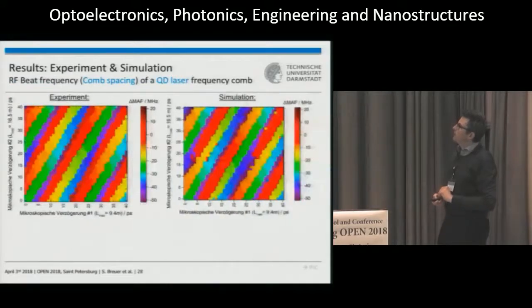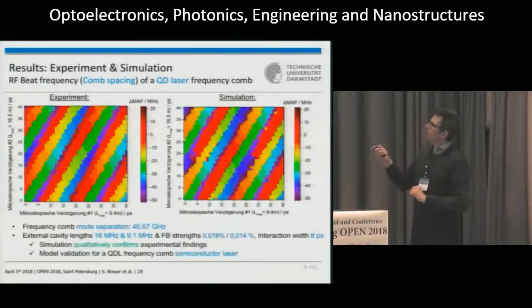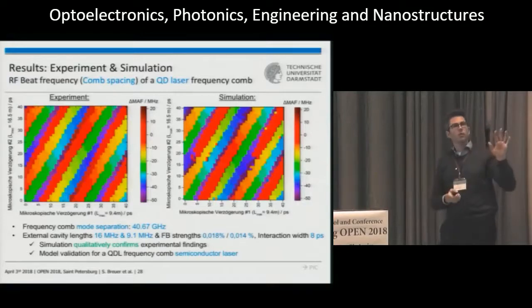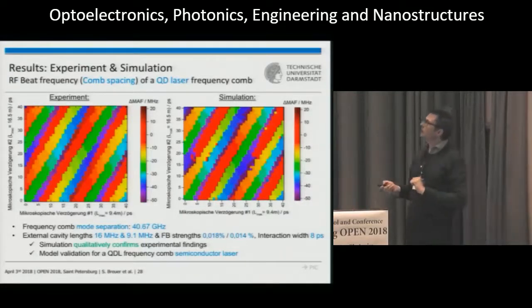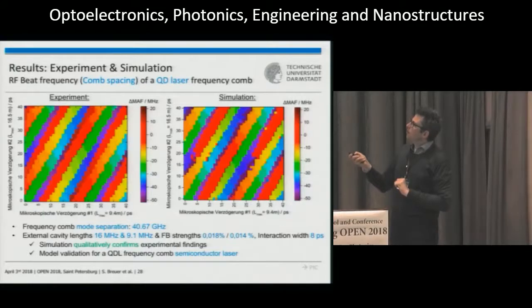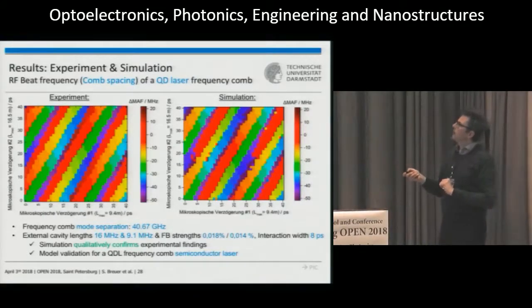And this is the final experiment. What we find is, again, the change in the mode comb spacing frequency as a function of the delay of the one cavity, and as a function of the delay of the second cavity. This gives you a tuning range of around 50 megahertz for a single section frequency comb laser. And these are simulation results with the stochastic model presented, which allow us to reproduce these results with qualitative agreement.